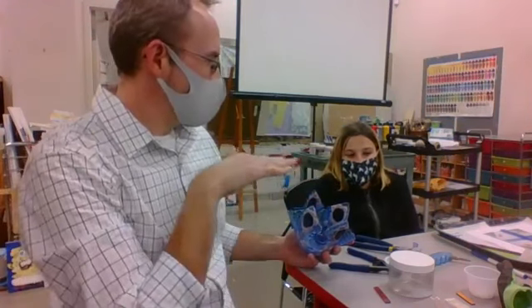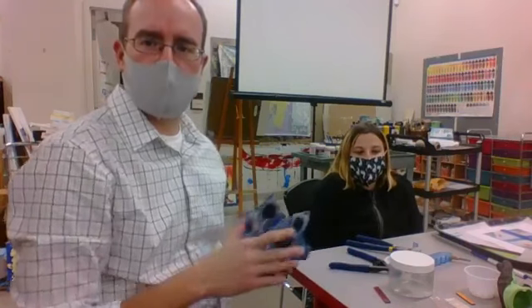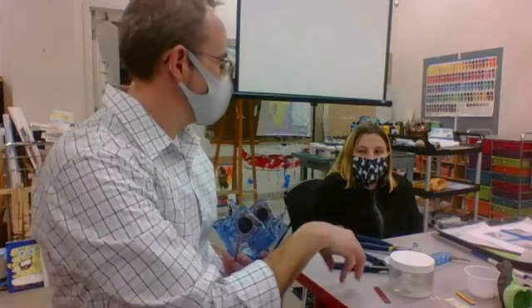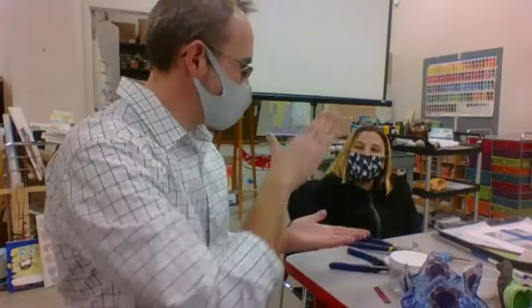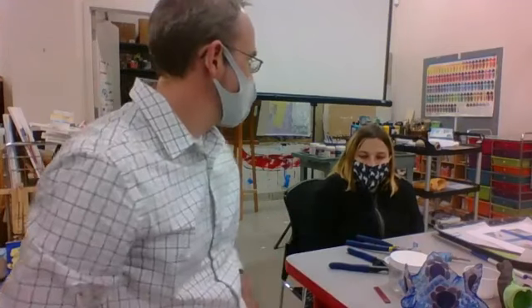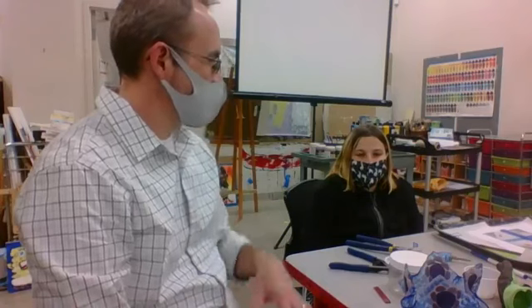It's a two-step firing process. The first step would be simply putting Charity's flat piece of glass in the kiln. That's going to fuse it up. You can go between the range of 1300 degrees and 1500 degrees, depending on the effects that you want. If we really want those trees to be distinct, you're going to put some ornaments on it too. If you want those to pop out and have texture, we'd use what's called a tack fuse, taking it to about 1350 degrees, where that heats up the glass to the point where it connects together, but doesn't fully melt into a single solid sheet. If you want those layers to merge flat and melt completely, we do a full fuse up to somewhere around 1500 plus degrees, which makes it nice and flat. Correct. Nevertheless, you need that first fusing in the kiln just to melt the pieces together nice and tight.